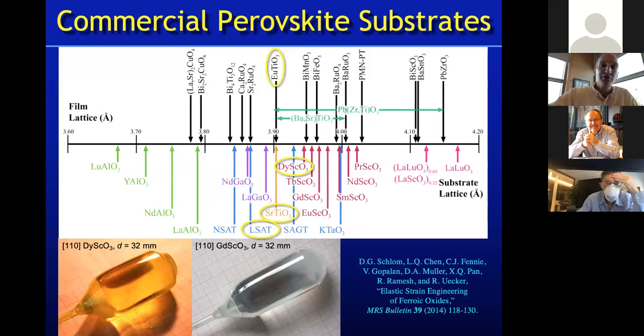That's the magnetic version of strontium titanate. So this is europium titanate. Europium is in the rare earths, and it's going to be europium 2 plus, titanium 4 plus, oxygen 2 minus, an ionic material, an insulator. And I mentioned it's just like strontium titanate in the sense that it's a perovskite. So in bulk form, it's cubic at room temperature, has a lattice constant of 3.905 angstroms. It's just like strontium titanate. Strontium titanate is also cubic in the perovskite structure with 3.905 angstroms.